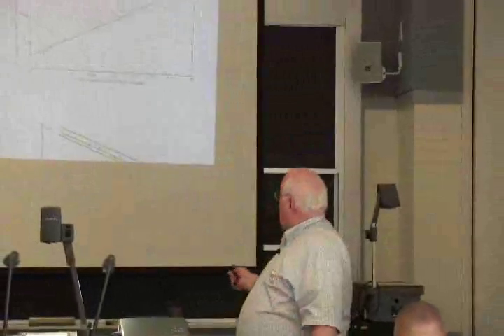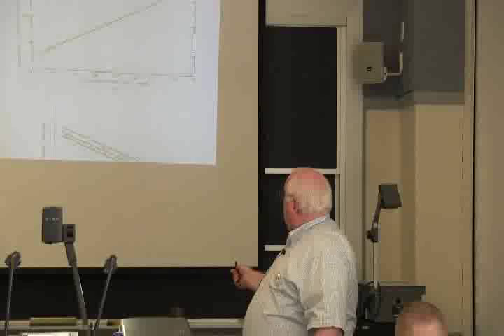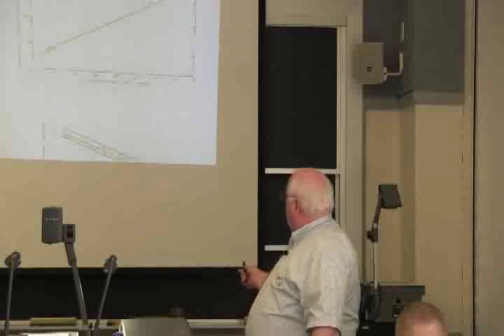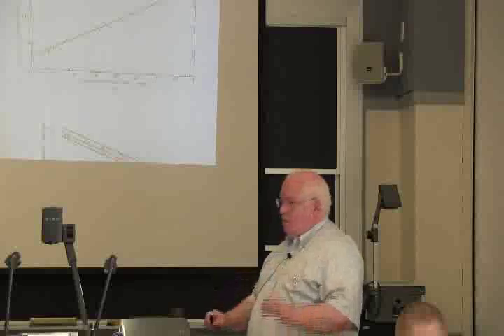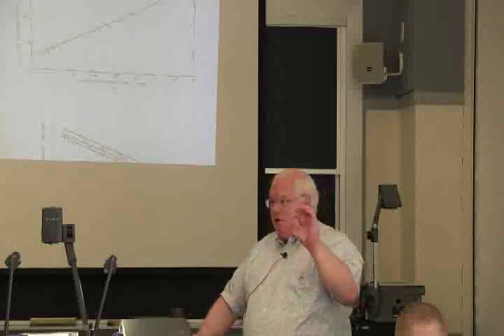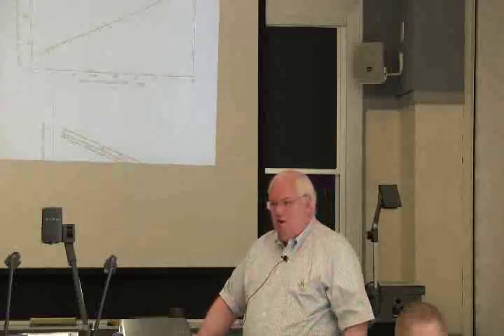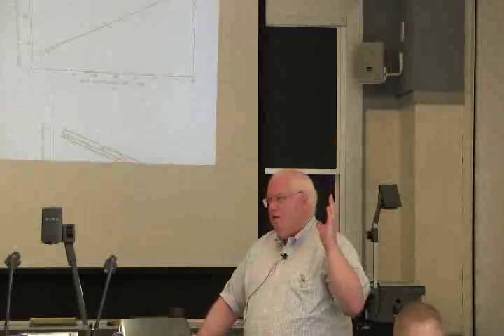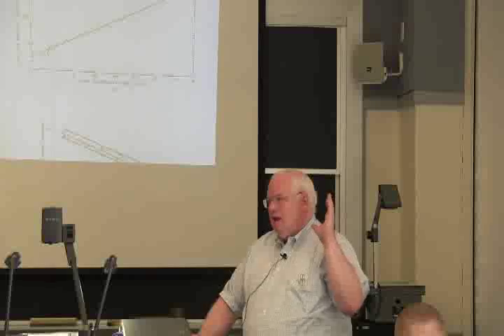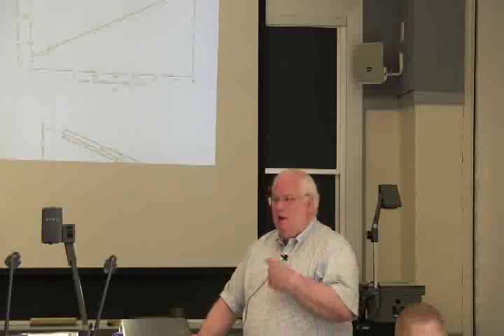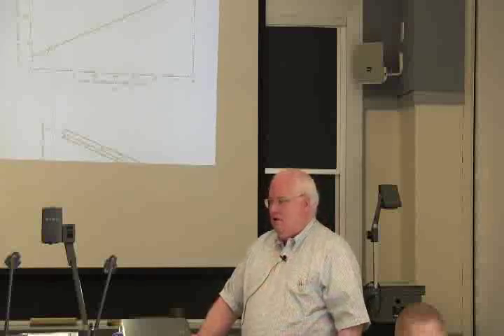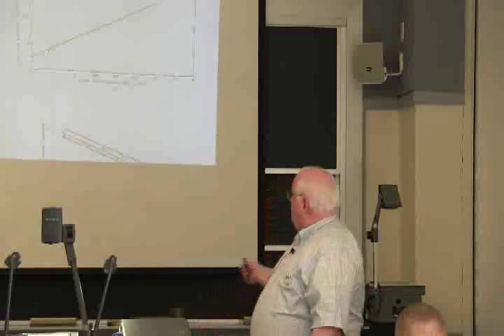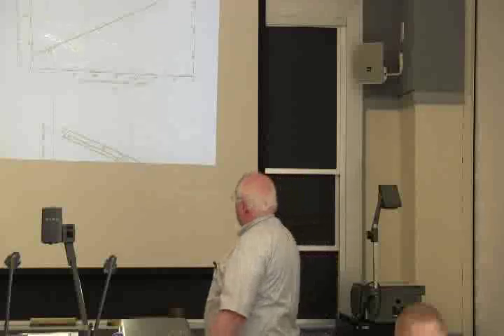If you cool very slowly, like a great big ingot, a 20-ton ingot, or a 20-inch thick piece of steel, you can have dendrite arms that are on the order of millimeters in size. Huge dendrites. And you can never diffuse away in the solid state that inhomogeneity. It would take millions of years at temperature. So we have to do lots of things to try to get fast solidification.